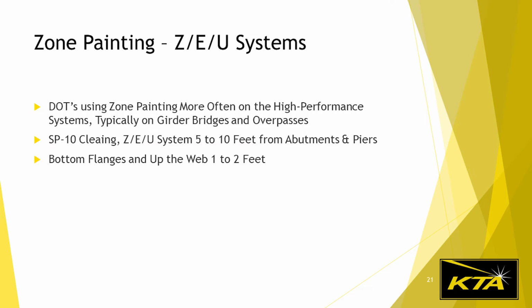We are seeing the DOT start to scope more zone painting with the existing high-performance coating systems. For the most part, they've held up pretty well with only localized areas of corrosion at the abutments and joints, especially if leaking from above, and on the fascia girders if close to the roadway due to vehicular salt spray. When they're replacing the coatings, we're typically seeing an SP10 with a new organic zinc epoxy urethane system applied about 5 to 10 feet from the abutments and from the joints as well.